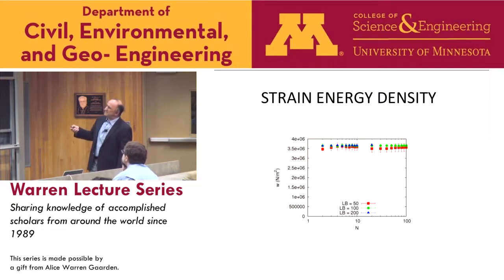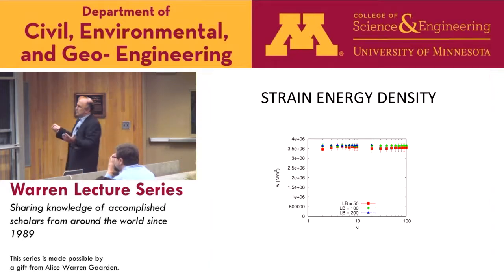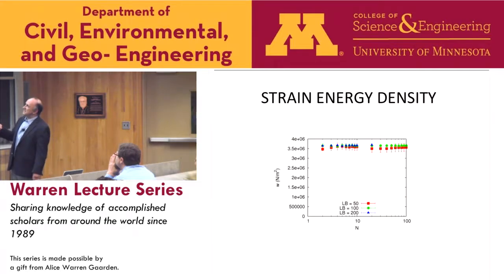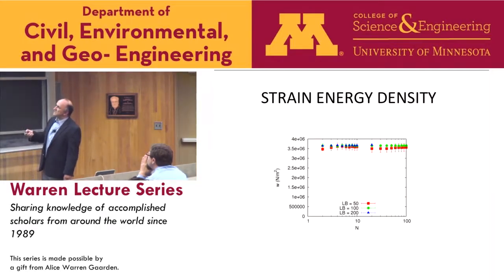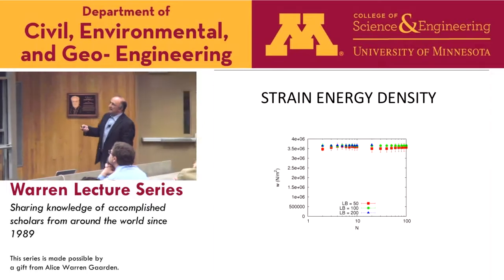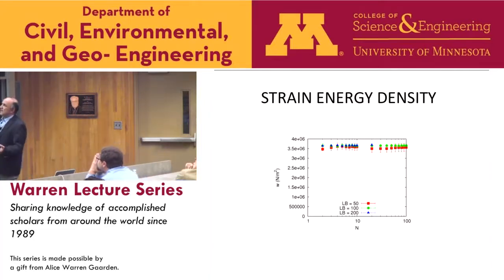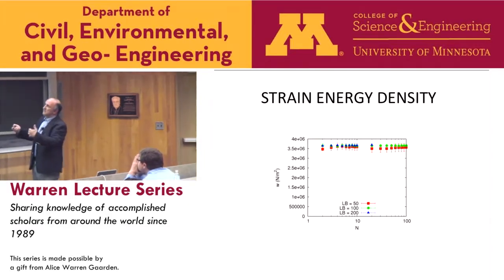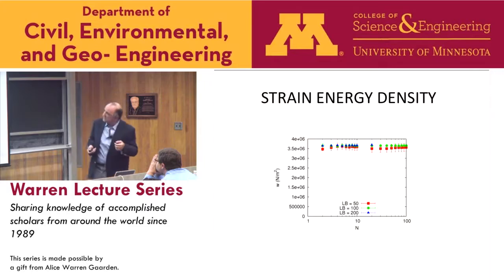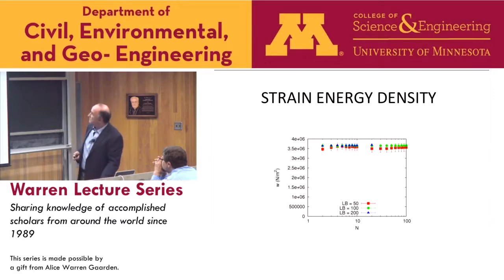And pretty much it's absolutely clear that you really don't need much to get to the nice region for statistics where more or less statistics doesn't matter. You can use boxes of size 50 and you can acquire statistics from a small number of specimens. So there are no surprises here in mechanical terms. Of course, as I mentioned earlier, it's very important to have large specimens to generate the proper statistics for the orientation density properties. Boxes of size 50 are pretty good.